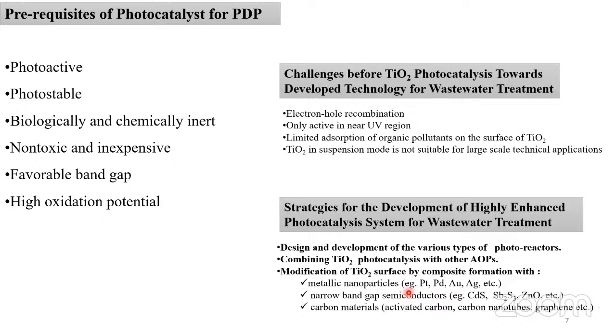And when you dope or decorate this TiO2 surface with platinum or any other metallic nanoparticles or metals, then what happens? They help us in preventing the electron hole recombination, and the absorption range of the photocatalyst is also extended to the visible light. So it all depends upon how you are preparing it, what kind of heterostructure or decoration or doping you are going to achieve. So these are typically the ways of doing it.